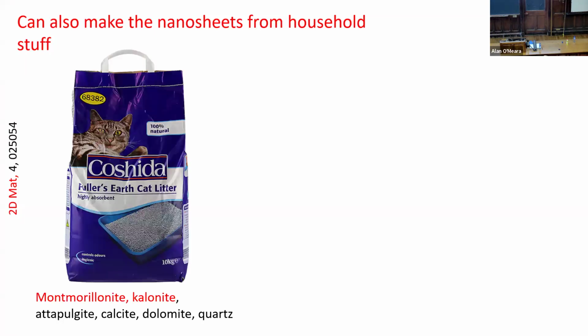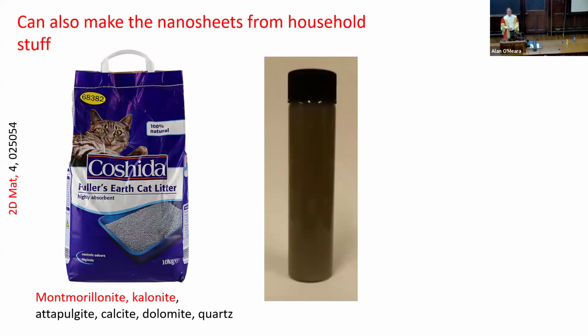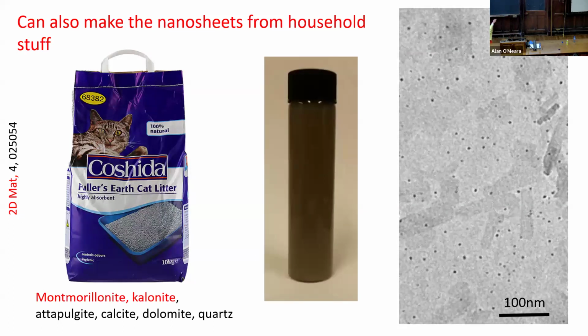So we don't just use household liquids to make 2D materials. We can use household materials as the 2D materials. And the first we attempted was cat litter. Because as anyone knows, cat litter is made of clay, and many types of clay are two-dimensional. And if you look at the side of that box of cat litter, it'll tell you what's in it. And those red ones are known to be layered materials, which should be convertible into two-dimensional nanosheets. So what we did was we took the cat litter, we ran it through our process, we got an ink, we looked in the ink with the electron microscope, and can you see just about there's very thin objects there? Those are two-dimensional flakes of montmorillonite. So these are 2D materials made from cat litter.